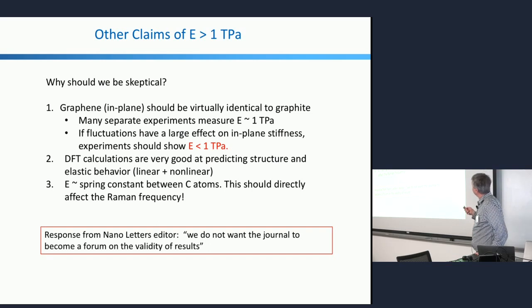Again, we're also getting numbers that, if you just think about graphene, in plane should be the same as graphite. The interlayer interactions are weak, right? That's why we can exfoliate this stuff. So you should get the same behavior for in-plane deformation of graphene and graphite.